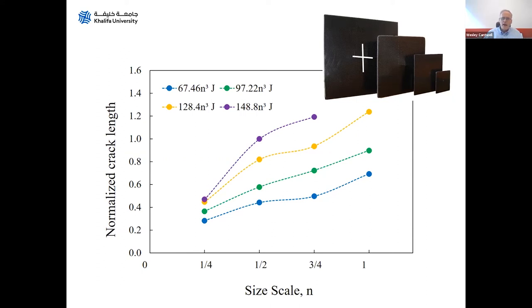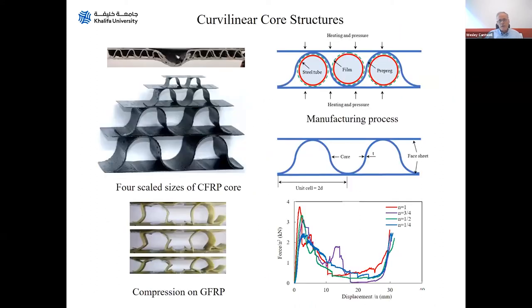And I think it's because our fiber damage is scaling as an n squared term. These fiber fractures through the length, through the thickness, there's no spread in the lateral direction. These are sort of two-dimensional cracks. And so we're putting in this energy as an n cubed, but this I think is an n squared relationship here. So we're getting more fiber damage than we would expect in the larger samples. So we're not getting anything like a scaled behavior there.